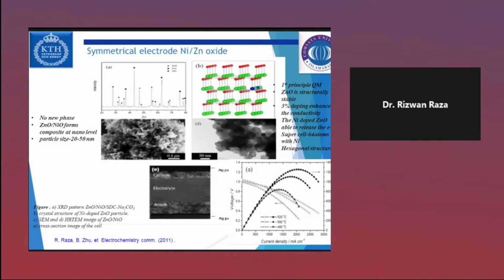Then if you succeeded to prepare some good electrolyte, then you have to go for the compatible electrode. Sometimes some electrodes, meaning anode and cathode material, are very good, but they are not compatible with the electrolyte. Then there are again chances of different ohmic losses as well as the overall polarization losses. So after introducing that electrolyte material, we first did some theoretical calculation using the DFT, and we have seen that